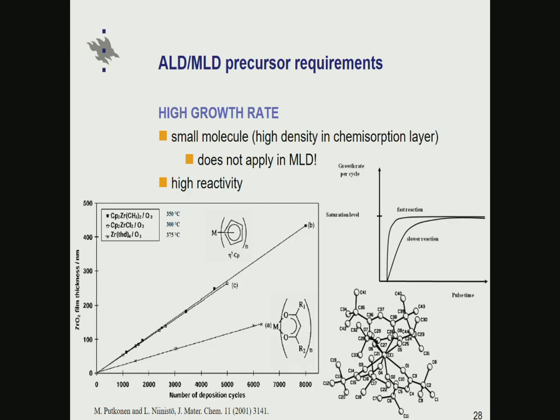High growth rate, of course, is very important. Here I mean high growth rate in terms of angstrom per cycle. The higher that is, the higher will be the overall throughput of the ALD process. In ALD, that typically means one should look for small molecules, small ligands, because then you can pack more of those in the chemisorption layer than if you have very large ligands which take a lot of space on the surface, and as a result the metal-to-metal distance in the chemisorption layer would be very large, and the packing density of metals would accordingly be low.